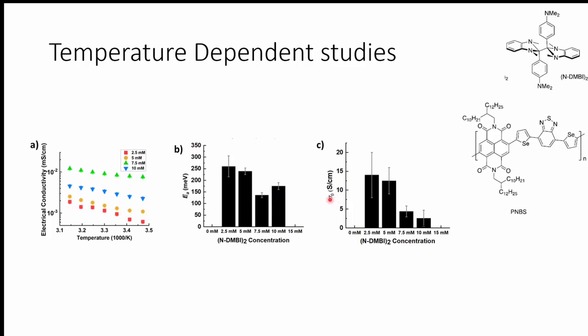Now, as for sigma naught, it is basically something called intrinsic conductivity. It's a pre-factor that tells you about the transport capability of your system. Normally you want your sigma naught to be as high as possible so that you get something pretty conductive when you dope it. But here we notice that it decreases with the increase in dopant, which means that although we're getting a conductive system, this system just doesn't really like to be doped, because we have a lot of disorder going on, and that is what's holding us back in terms of conductivity, although we expected it to be pretty conductive.